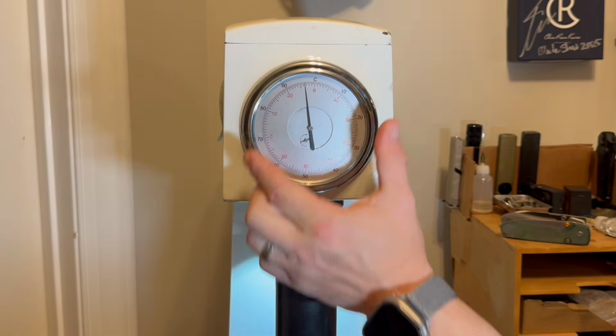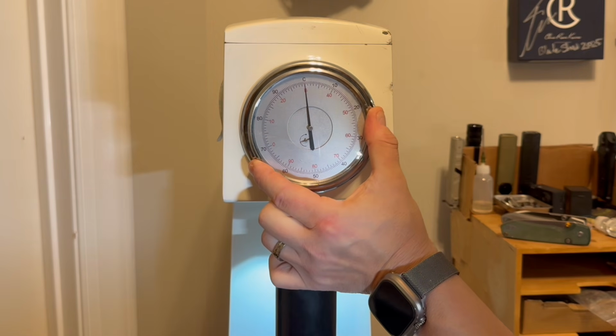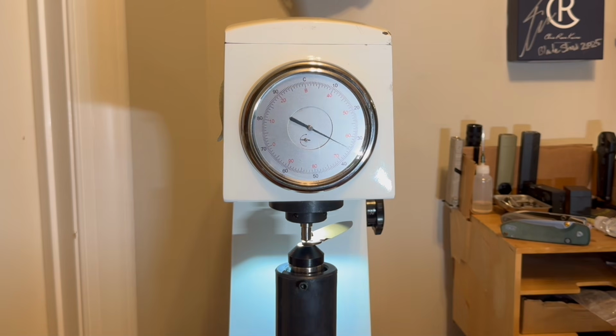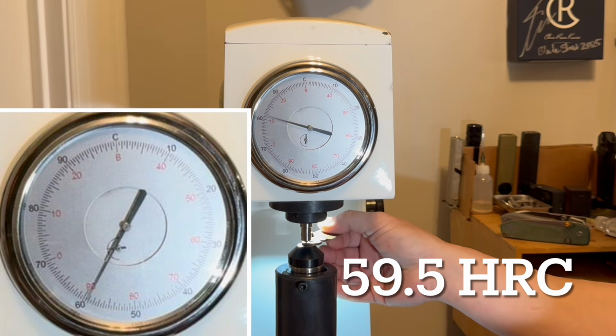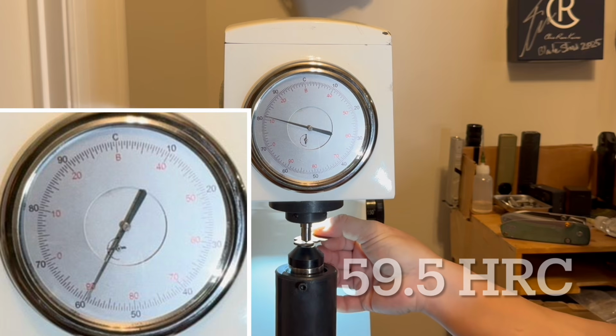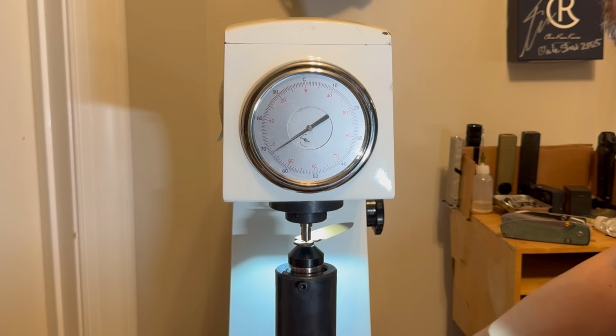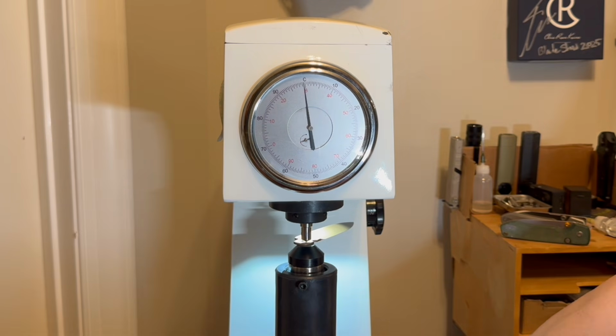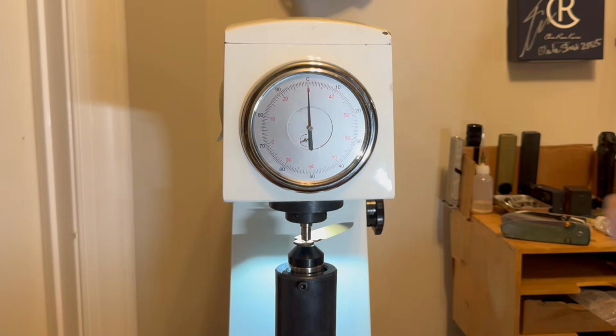I am not sure what kind of coating they use. They did not advertise it. I suspect PVD coating, but it could be DLC. I'll later examine it under the microscope and hope some of the coating experts will chime in. 59.5 HRC on the first poke, which is very close to the uncoated blade, indicating a solid planning in their heat treatment and coating processes at whoever is an original manufacturer for this knife.